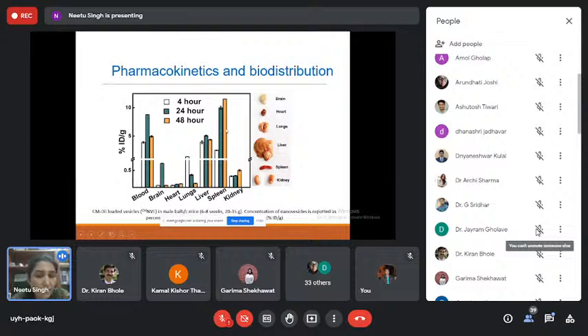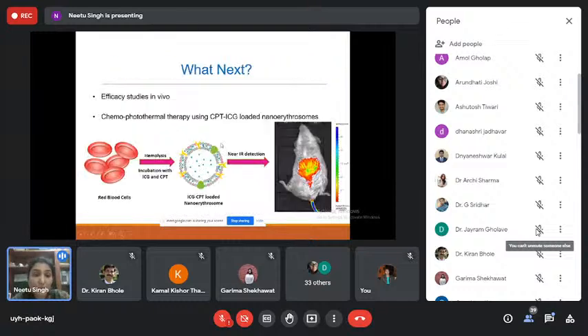It follows a similar degradation pattern as the RBCs. RBCs get cleared in the liver and the spleen, and you can see that spleen over time had higher concentration, which means that it is being treated by the system as RBCs, and it then sends all the RBCs to the spleen to get degraded, and this is exactly what is happening here.